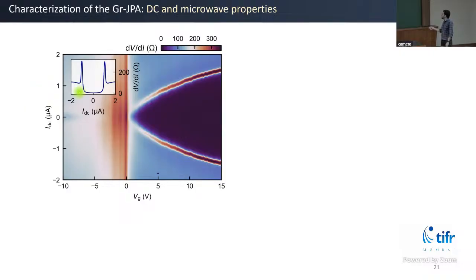And in this blue regime, basically the resistance is 0. So the junction has no resistance. It can carry supercurrents basically. And then you increase the bias current, and eventually it turns normal at this point. So you see a peak in resistance. And this boundary basically says the critical current, which is getting enhanced by the doping effect through the gate.